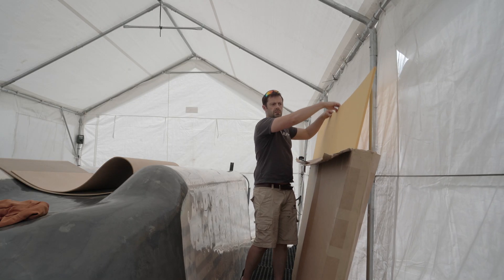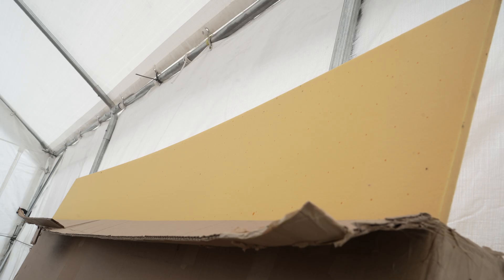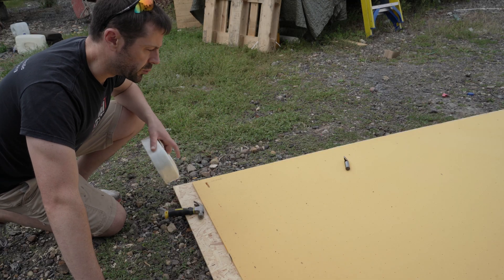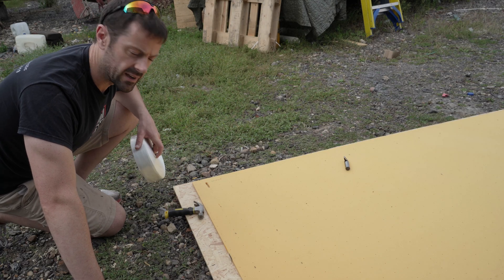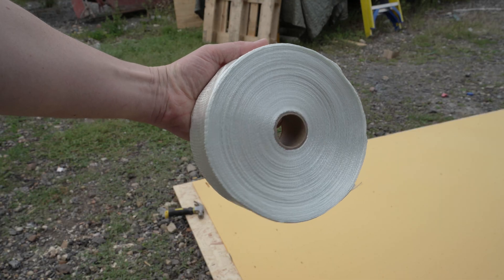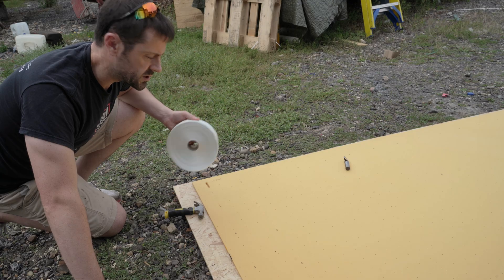These very expensive sheets arrived some weeks back, but here we go for a proper look. They are optimised for resin infusion with the perforations, but they will still be useful for a less exotic vacuum bag job, pulling vacuum across the core. We're going to pass little tongues of glass fibre through the foam, and that's going to mean we can hold the two sides together even more strongly than purely an epoxy bond to either side. We're using the unidirectional glass because it's got an amazing adhesive quality to the two laminate layers — glass just likes to stick and encourages really good interlaminate strength without the chance of delaminating.